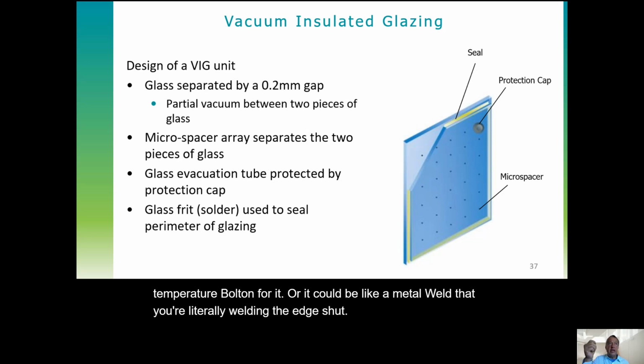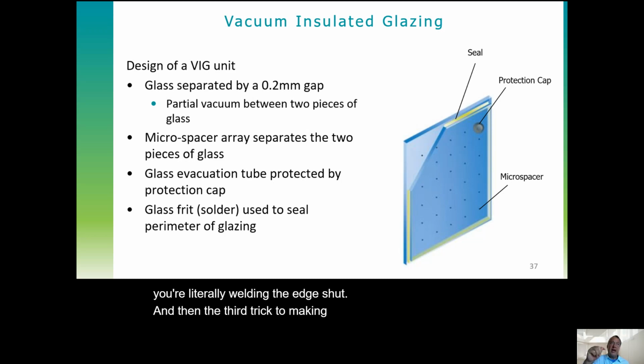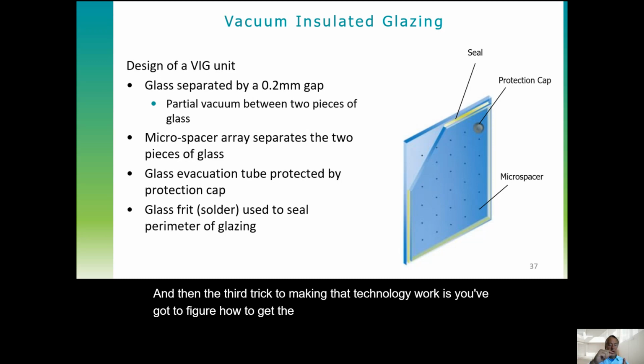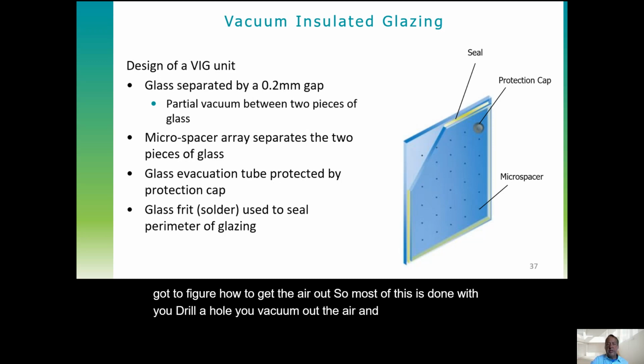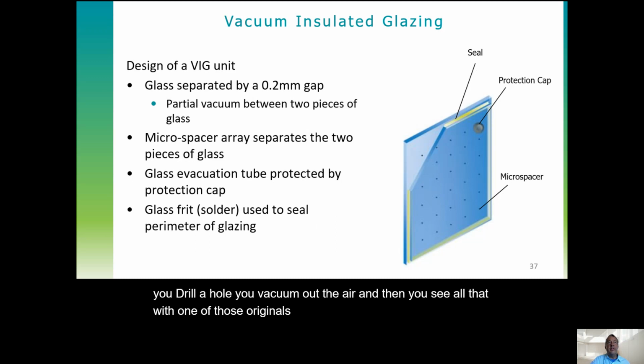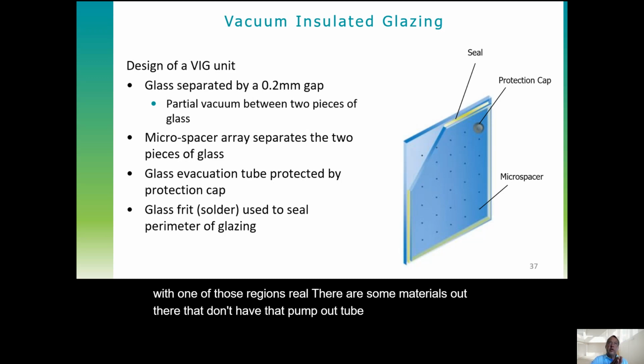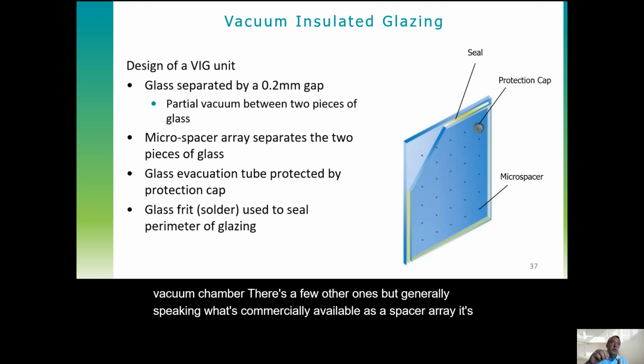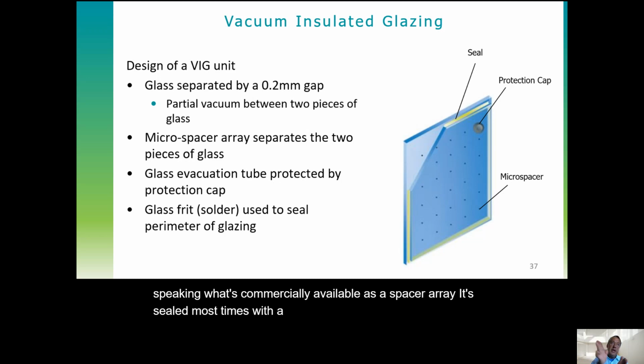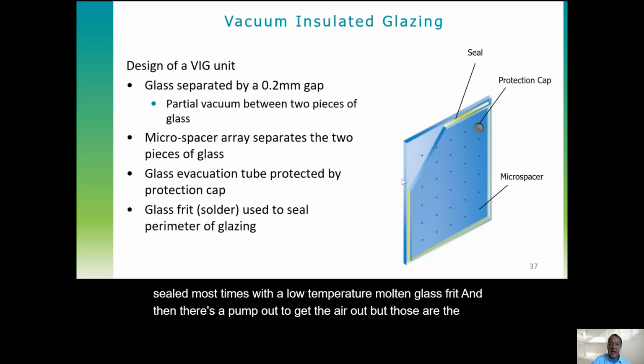And then the third trick to making that technology work is you've got to figure out how to get the air out. So most of this is done with, you drill a hole, you vacuum out the air, and then you seal that with one of those rigid materials. There are some materials out there that don't have that pump out tube. They're done in a vacuum chamber. There's a few other ones, but generally speaking, what's commercially available has a spacer array, it's sealed most times with a low temperature molten glass frit, and then there's a pump out tube to get the air out. But those are the three tricks on how to make the VIG design.